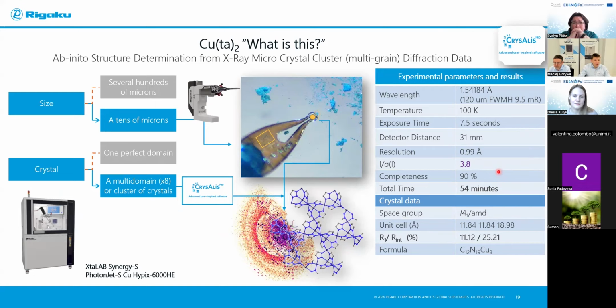Basically, with the development of single crystal instruments, when we have super bright microfocus sources, you can go with crystal sizes of tens of microns, not several hundreds. That's very often something people don't think is possible. And the crystals don't have to be a perfect single-domain crystal. We easily and routinely measure multi-domain crystals, up to 8 domains or even more.